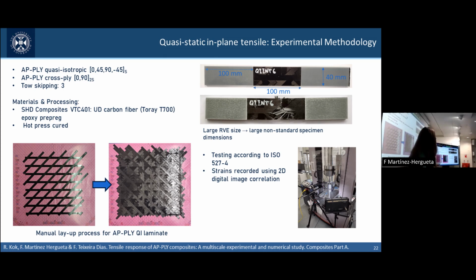We also manufactured some baseline angle-ply laminates, just using conventional layers for reference. The material that we employed was a carbon fiber epoxy, and we manufactured them by hot pressing in a hot plate press. So something to mention before going into the results is that since we are using tapes to create a mesostructure, we might end up with